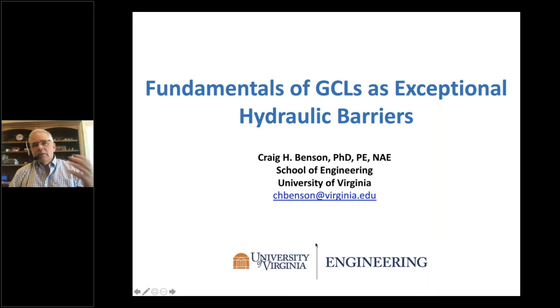You can run some shake-type tests, where you take the subgrade with a deionized water eluent, like a batch test, shake it, and then look at the chemistry of that supernatant. That's one way to get at that chemical composition. Another process is you can take the subgrade soil, and this is one that I tend to prefer, and permeate it with a moderate ionic strength solution.